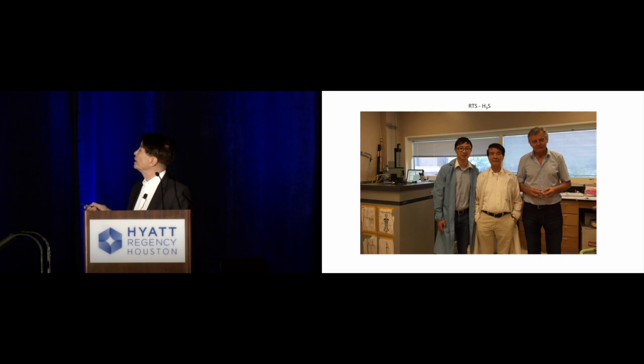So when the hydrogen sulfide was first discovered, by Mikhail Eremets, he only measured the resistivity. As you know, with such a small sample under such a high pressure, it's very difficult to do the experiment. So if you can do the Meissner effect, then there's no doubt. If you can see it, that's a proof of superconductivity.